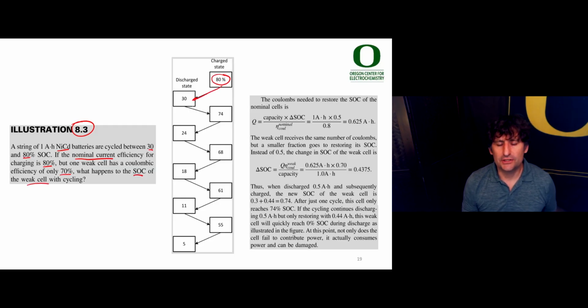You discharge to 30%. Now, when you go back to charge it, all the other cells get back to 80%, but you only get to 74% because the coulombic efficiency for the weak cell is lower. Then when you discharge it again, you pull out that same 50%, going from 80 to 30, now 74 to 24. All the other cells are going down to 30, but this particular cell is going to 24. And if you repeat that, you can see that eventually the cell fails. It goes down to very low states of charge, and that can actually damage the battery and in fact consume power if you're trying to extract charge from a battery cell in series with others, and that cell doesn't have any charge left to give.